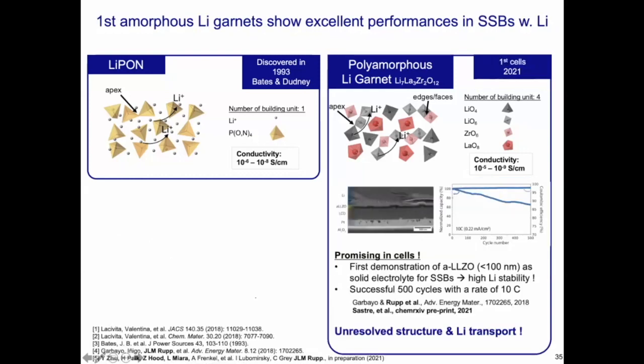And what excited me a lot is that there have been recent demonstrations, after our publication of the existence of the amorphous lithium garnet structures, that these were integrated in first cells and show very high cycle stability. There are first demonstrations of 500 cycles at a C rate of 10. So these amorphous lithium garnet structures could be interesting protective layers later for various structures, ranging from sulfide- or oxide-based cells, because they're also made at quite low temperatures. So they could be good protective coatings for lithium.